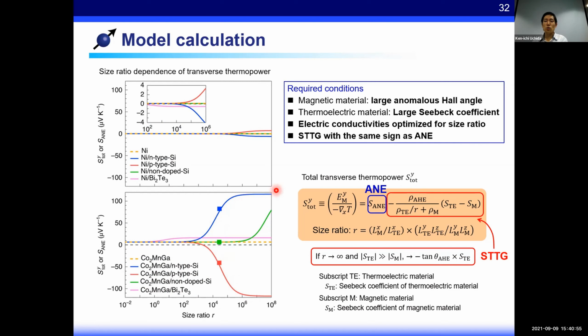We found that the total transverse thermal power can be larger than 100 microvolt per Kelvin by optimizing the combination of magnetic and thermoelectric materials, and also by optimizing their dimensions. This value is more than an order of magnitude larger than the anomalous Nernst coefficient reported so far.